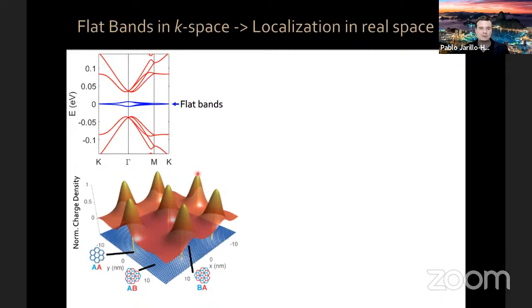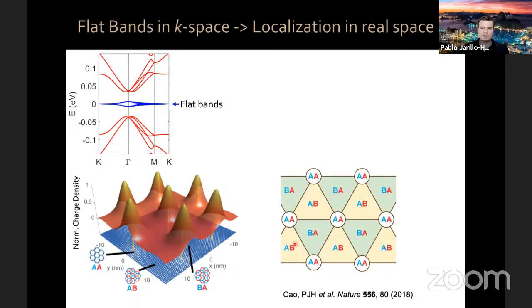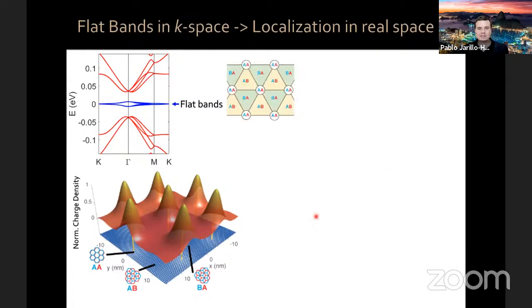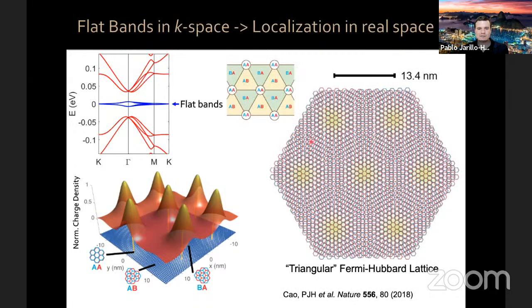They like to sit in regions where locally the two graphene sheets have AA stacking. These regions where electrons like to sit are tunnel coupled via regions of local AB and BA stacking. Because you have this angle, this local registry between the atoms varies as you move along the two graphene sheets. So then what we end up with, from a top point of view, is our system, which consists of these AA regions where electrons like to be. These regions are separated by regions of AB and BA domains. This is now a slightly more realistic schematic.